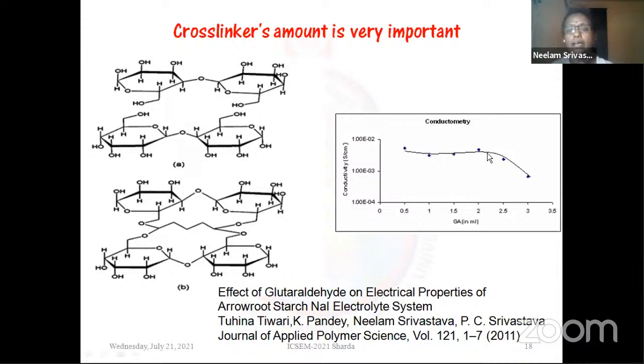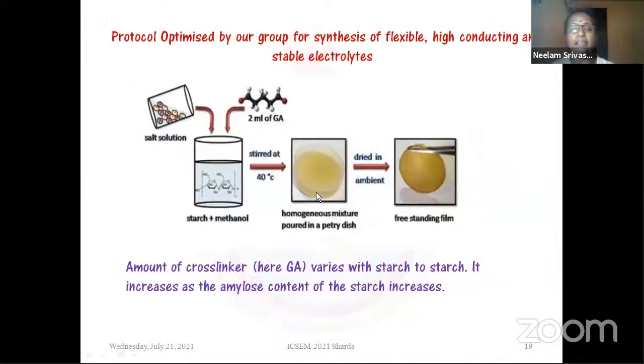So we found that if we put in 1 gram of salt, and 2 ml of GA, then the system is quite good. We can easily develop a freestanding, nicely transparent film. And the system preparation method is very simple, doesn't need any technologically advanced instrument, nothing is required. Simple, take beakers, use salt solvent, use starch solution, make salt solution, and stir them at a proper temperature. This temperature changes with the different starch. This is for the potato. Like this wheat, if you go for the wheat, it requires 70 degrees. So it depends upon the starch. So you have to vary this, and put some amount of the GA in the system, let it dry, and you will end up with the nice freestanding film.